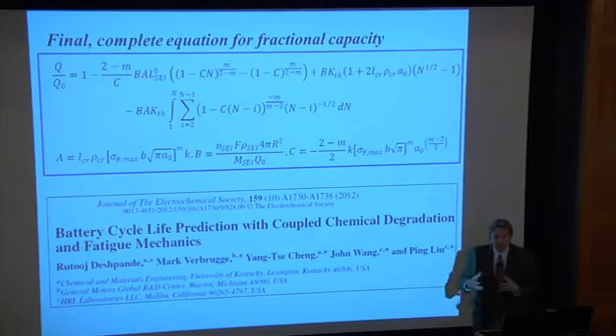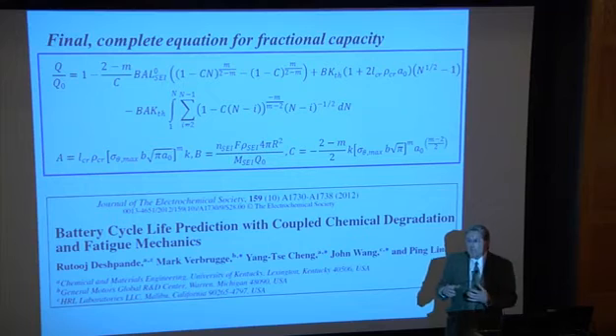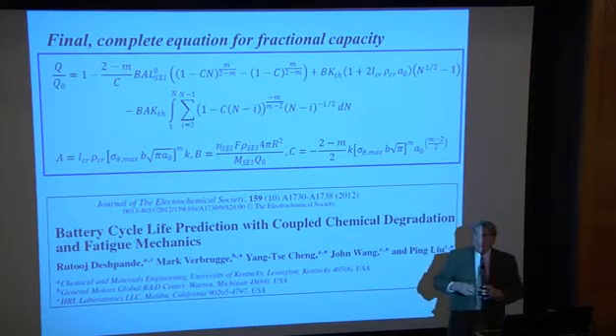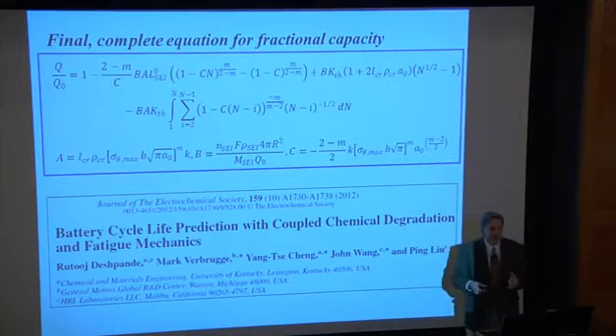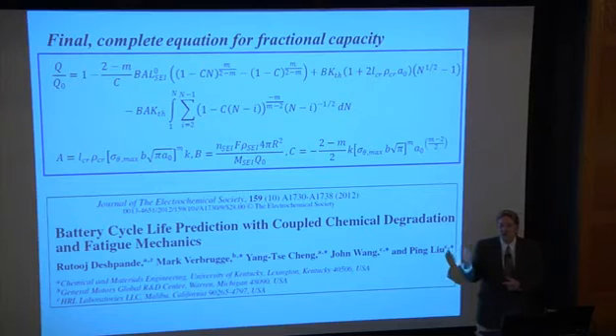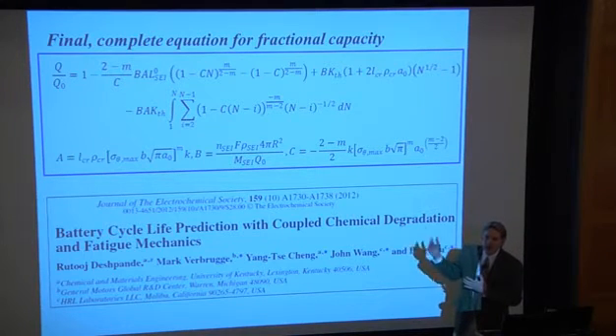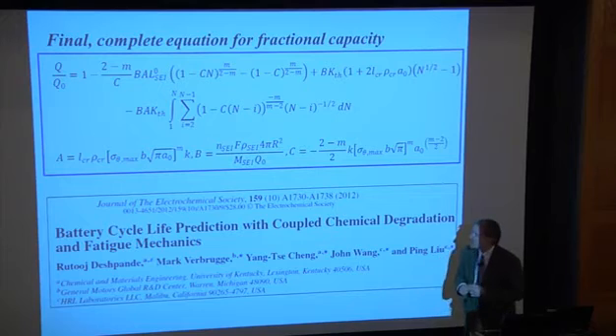And we use Paris law to try to track crack growth. It's a very empirical approach. It's from an energy balance. I would argue it's acceptable because people publish volumes on Paris law constants in material science. But that's where we are right now as far as state of the art in modeling of these systems.